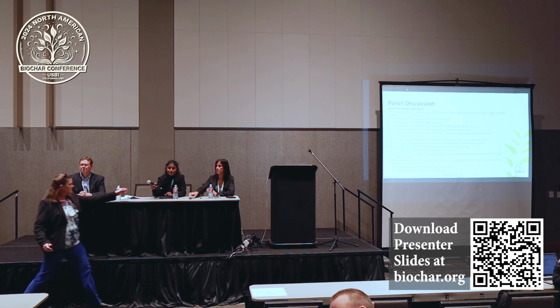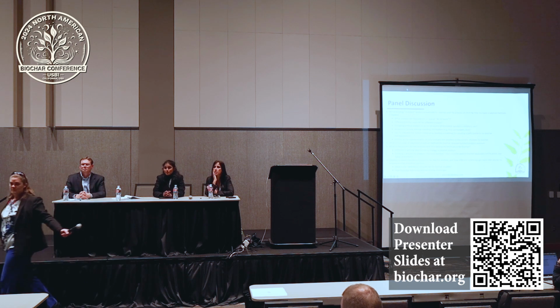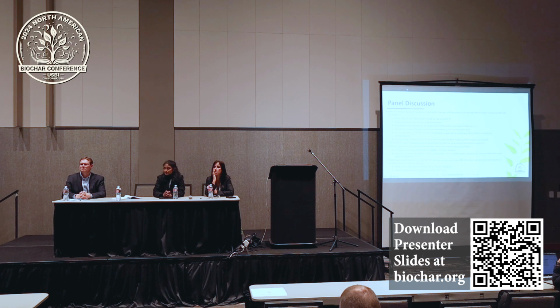Like to augment Kate's greasy assay. It was actually a test that Tom Reed developed years ago called the soap test. Basically, you take your char, you rub it on your hand, and then you go over a pail of cold water. You rub it in the cold water. And most of that comes off. That's called passing the soap test. If you need soap to get the black off, that's the grease that came out of the chunks. And you now have defined greasy char. That is literally called the soap test. It's extremely accurate.